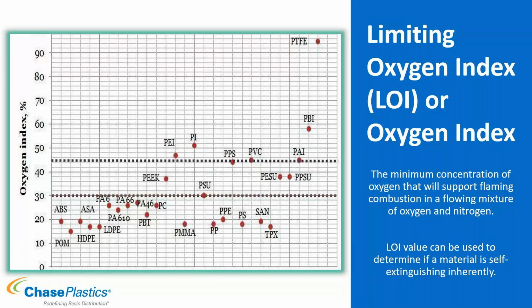If you're trying to have a fire, it needs oxygen to continue to burn. For materials that require a high level of oxygen you're not able to achieve everyday - the average oxygen we're sitting in right now is about 21 to 22% - any materials above the 30 line require more oxygen than is found in our everyday air to continue to burn. These materials above the 30 line are considered self-extinguishing, meaning you don't have to add anything to them; they automatically put themselves out because there's not enough oxygen available in the air to continue to burn.